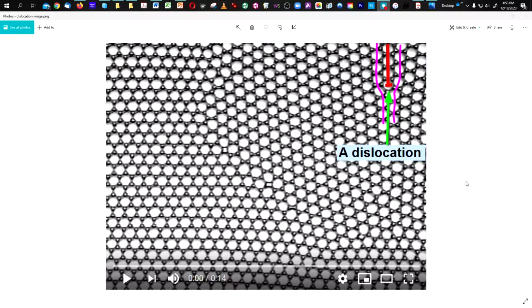And what I'm going to show you in the video, we're going to play it slowly at first, is that there's going to be a stress applied. In other words, essentially we're going to try and deform this crystal. And I'll show you in a minute, though, this dislocation is going to work its way over and allow the crystal to deform until it gets to the grain boundary. And then because the alignment of the next grain is different, that dislocation can't move anymore, and it gets pinned down at the grain boundary. We call that dislocation pinning. And because the dislocation can't move anymore, the crystal can no longer deform. And we'll talk about what that means in terms of the strength of the material in just a minute. So let's go to that video.